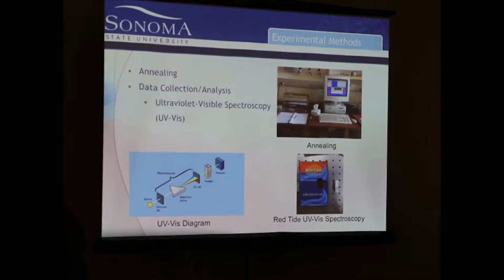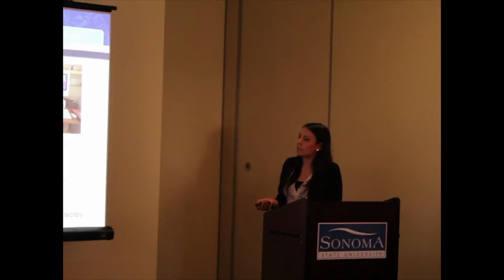After I do that with various times and temperatures, I check it in the UV-vis, also known as the ultraviolet visible spectroscopy. And this is the one I use. It's fairly small. Most of those you see with cuvettes with liquids in them, but since mine's a solid, we have our own, and it just has a hole in it, so I can have the sample be on it and the lights can still shine through. Essentially what is happening in the machine is that you have this source light, shining through a prism. The light bends at different wavelengths, and then it goes through the sample, and the detector detects how the glass and the different wavelengths of the light interact. Through that process, I get my data.